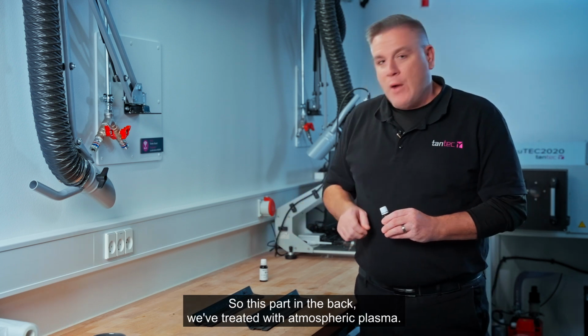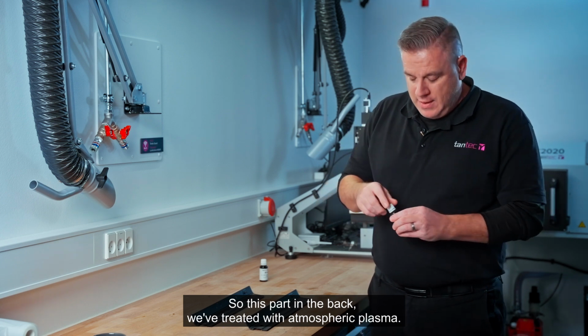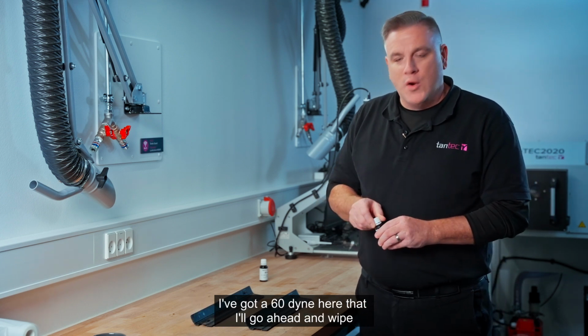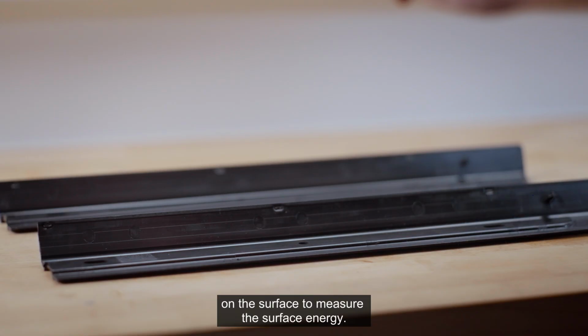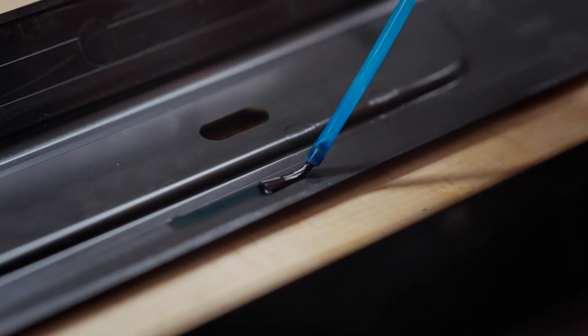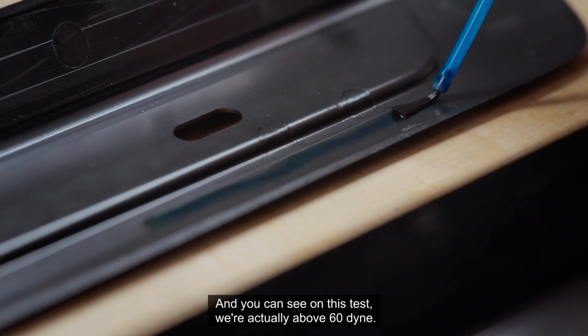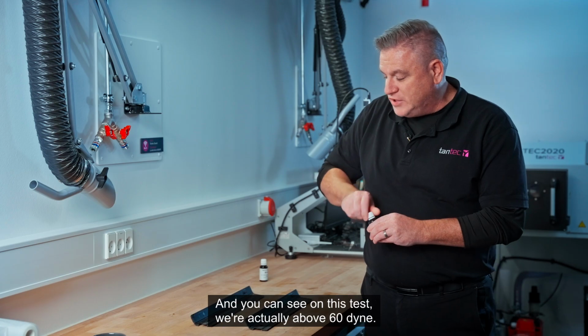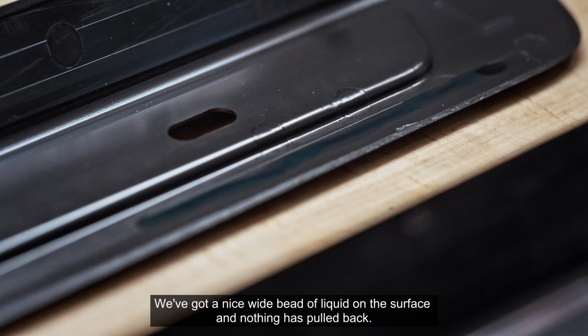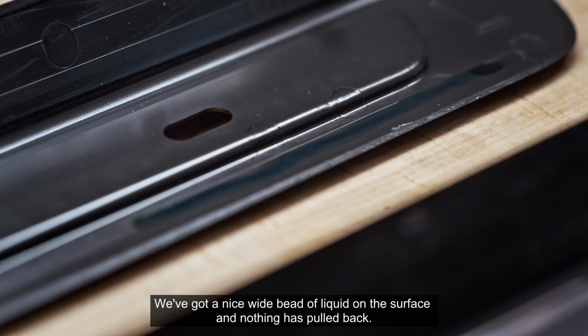So this part in the back we've treated with atmospheric plasma. I've got a 60 dyne here that I'll go ahead and wipe on the surface to measure the surface energy. And you can see on this test, we're actually above 60 dyne. We're completely wetting out. We've got a nice wide bead of liquid on the surface and nothing has pulled back.